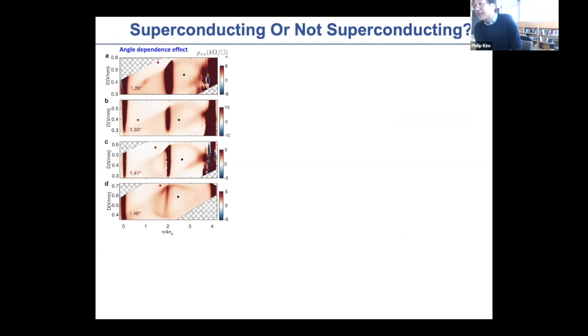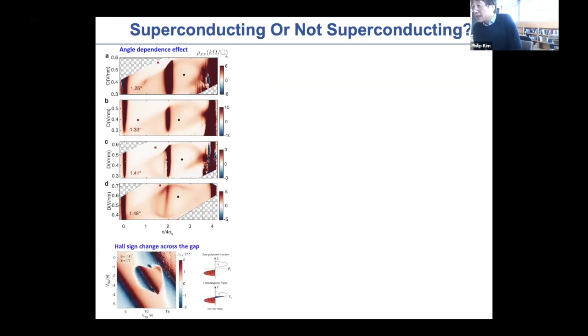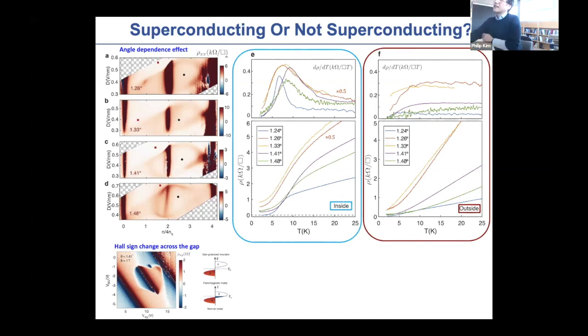It is true that between 1.2 to say 1.5 degrees of the twisting angle, we should be able to realize this spin polarized correlated insulator by tuning the displacement field, and that is what this shows, all the demonstrations. Then when we measure this doped correlated insulator region, we do see a generality that indeed in these regions near this correlated insulator, the resistance drops rapidly to a very small value, close to zero, but not all the samples show zero resistance.